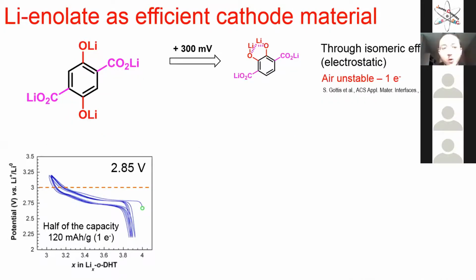So there are several ways. We keep working with the same molecule. We have a lithium enolate carboxylate. So what we need to do here is to change the molecular structure and find ways to increase that potential. The first way is just to change the isomery of this molecule. Here you have a para configuration. If you shift from para to ortho configuration, you will have an increase of the potential of 300 millivolt.